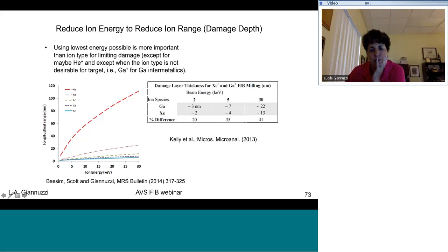So we look at this experimental work that shows damage layer thickness for xenon and gallium. At a beam energy of 30 kV, we see a huge difference, 41% difference between the depth of damage of xenon with respect to gallium. Of course, xenon is a higher mass, heavier mass, so it's going to produce less damage based on what we know from our ion-solid interactions.